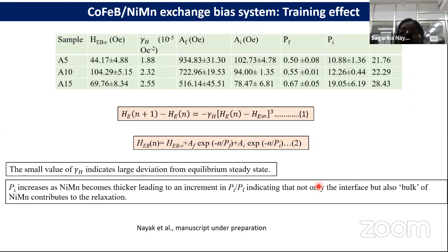Now we have analyzed the data. In this data, we found that the gamma h value calculated from equation 1 is one order of magnitude less than in the previous study, indicating that the relaxation, during field cooling, of the metastable state that is created, and during the training effect, the relaxation is more in this system.